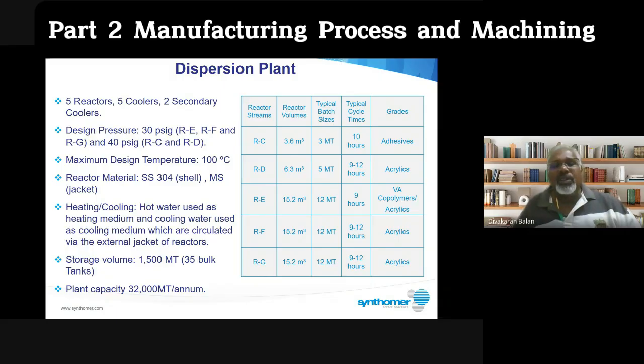Okay, and then cooling water is used as the cooling medium. This is not chilled cooling water, it's just normal water at around 28 to 31 degrees Celsius, so that we use to cool down the reactor. The cooling medium is circulated via the external jacket of the reactors. So you have pumps which bring the normal water into the reactor jacket, you circulate it, and it goes back out to the cooling tower. So that's how it flows.